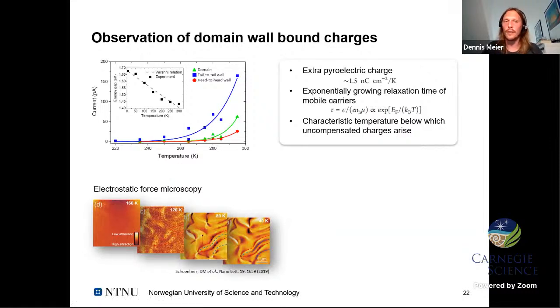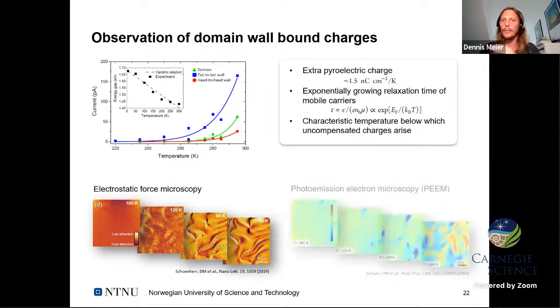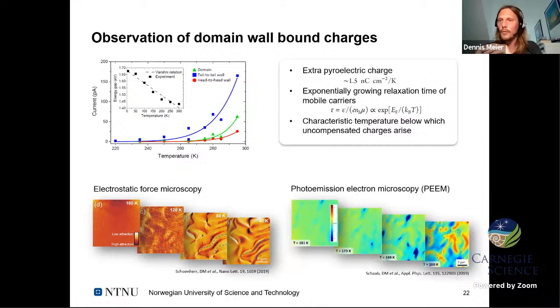It's not just an effect you can see in electrostatic force microscopy. You can also measure that same effect with photoemission electron microscopy, showing that it's a universal phenomenon. When you go down in temperature, first there is no potential difference, and at some point I see a pronounced potential at the position of the domain walls, because I no longer screen them. And that's a very important thing, because it's one of the rare examples of an unscreened ferroelectric interface which is still stable. So we have polarization charges pointing towards each other, polarization diverges, and the system still keeps the domain walls.